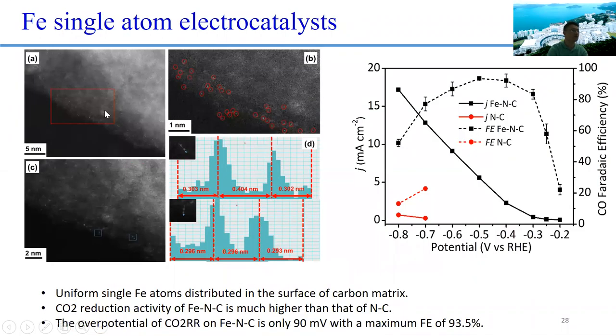So this is the iron single atom. If you want to see more clearly, each white dot is a single atom, and you can use this to identify them. The faradaic efficiency for CO production is very high for the single atom. If you compare with the nitrogen-doped carbon, basically nothing, but for the iron-doped one, very, very high.